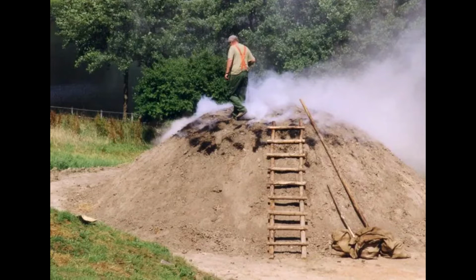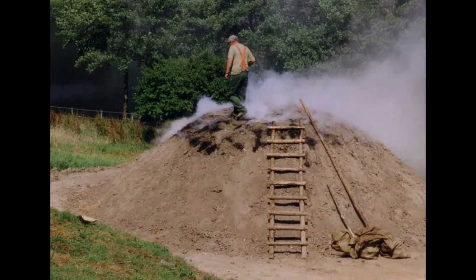The burner can then influence the process by either puncturing or sealing holes in the kiln to increase or decrease airflow, working to achieve a balance where there is just enough oxygen to keep the fuel burning, but not enough that the wood catches fire in earnest. A decent-sized kiln typically took about 6 to 8 days to complete the carbonization process. Once it cooled, the kiln could be broken open and the pile of effectively pure carbon extracted.